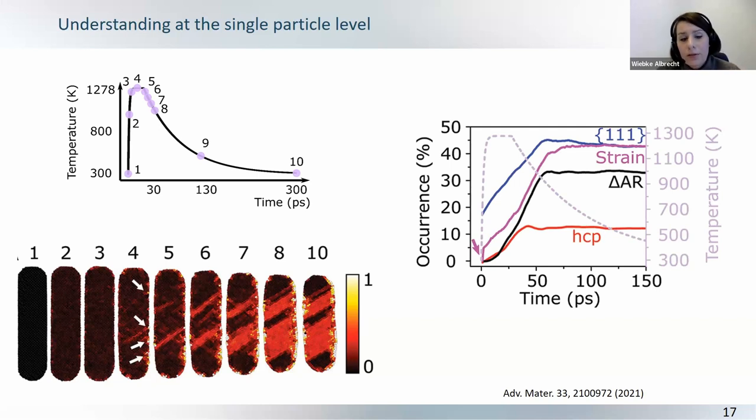So, you first start off with surface diffusion, then atoms feel, or the system feels strained due to that, and evolves into these single crystalline with lattice defects.